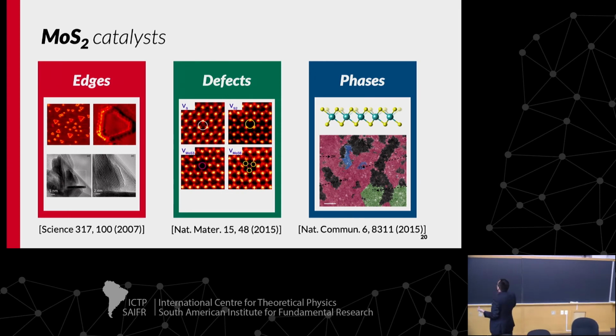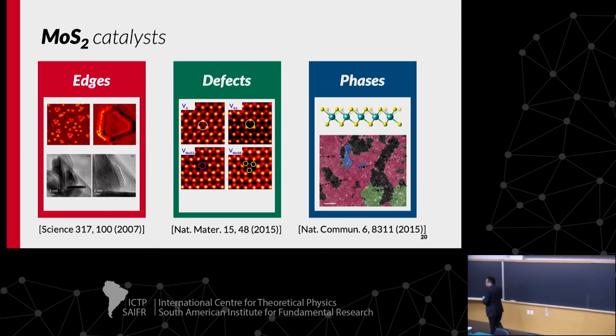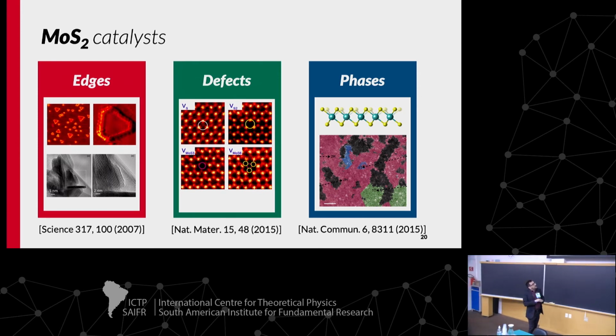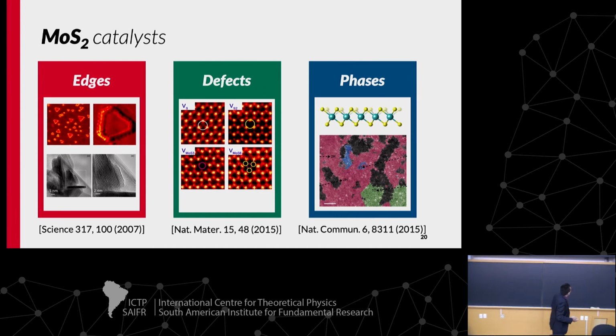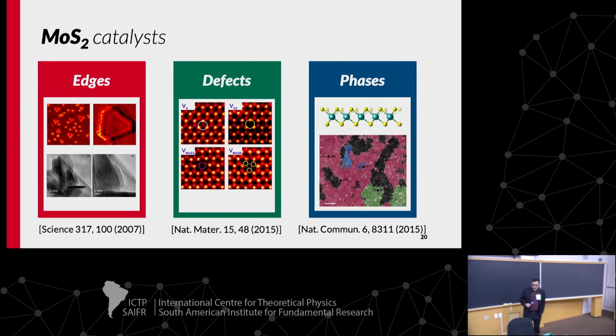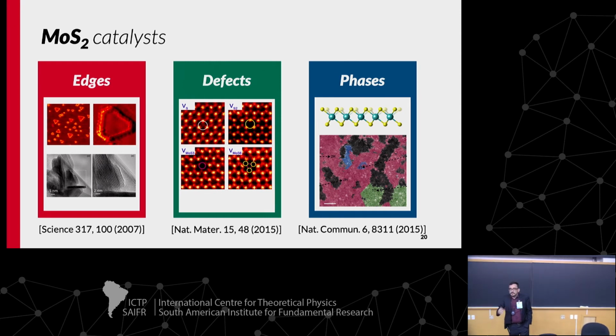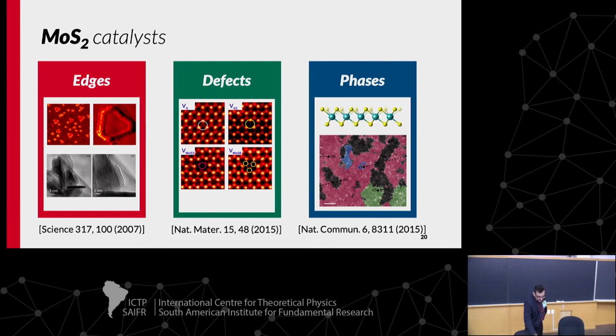Another strategy is to use intrinsic effects, like sulfur vacancies in MoS2, and the phase transition of this 2H to 1T phase, actually 1T prime, because we have some distortion in the lattice. And when we have this phase transition, the material converts from a semiconductor to a metal, and the catalysis is much better than the basal plane of MoS2.